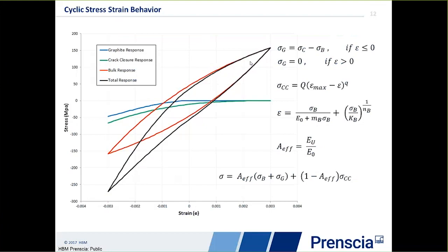What Downing did was to take that and actually break it into several components. The first component he describes is looking at this hysteresis loop. He basically recognized that the height of going from the unloading curve to the loading curve across this hysteresis loop was symmetric. And so he basically decided he did not have to go in and have this asymmetric behavior. He started out with a hysteresis curve that was symmetric.